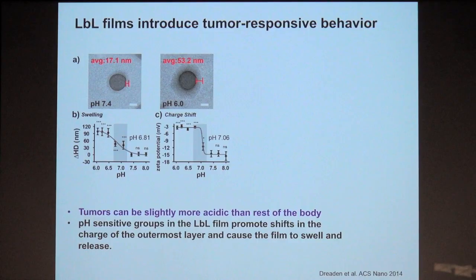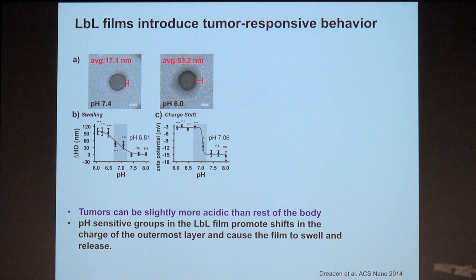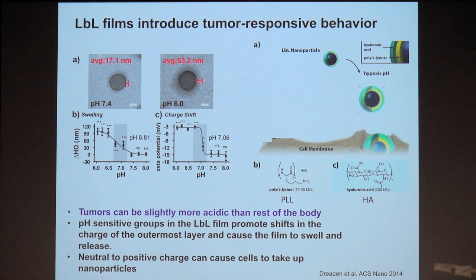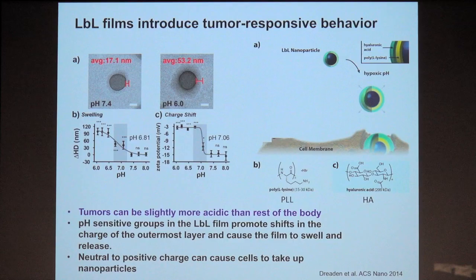And that's how we think we can deliver the drug or the siRNA, because when it gets taken up by the cell, it goes into an endosomal compartment that goes down to very low pHs, 5.5 to 6. However, in the in-between space, when it's in the tumor tissue, it undergoes a more subtle change. It becomes, rather than a strong negatively charged nanoparticle, kind of a neutral one. And that loss of charge makes the nanoparticle a system that the tumor cells become kind of interested in. It's no longer repulsive. It's got kind of a softer, fluffier layer. And it turns out that it undergoes these very nonspecific, routine interactions with the nanoparticle that lead to engulfment of the nanoparticle into the compartment of the cell.